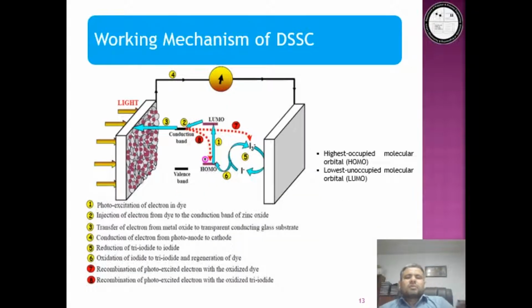So what is the working mechanism of DSSC? As you can see in the figure, dye molecules are attached to the metal oxide semiconductor through a covalent bond. The adsorbed dye absorbs solar radiation and electrons in the dye become excited. So electrons tend to move from a low energy level to a high energy level. The highest occupied molecular orbital is considered the low energy orbital, while the lowest unoccupied molecular orbital is regarded as the high energy orbital. The electrons are then injected into the conduction band of the metal oxide semiconductor.